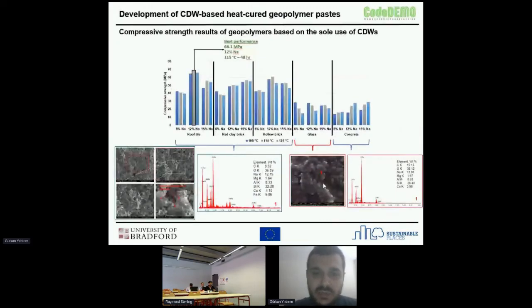This is the midterm results. This is the compressive strength results of geopolymers, which are based on construction and demolition wastes. But this is our first step of our work. So we focused on single utilization of these source materials: roof tile, red clay brick, hollow brick, glass, and concrete. And we only used sodium hydroxide as the alkaline activator. And in order to get a reasonable compressive strength level, we needed to cure these materials in an oven at 105, 115, and 125 degrees, because the lower temperatures didn't give us good results in terms of compressive strength. So we increased the level of heating. But just keep in mind that this is only with sodium hydroxide and only with single materials.